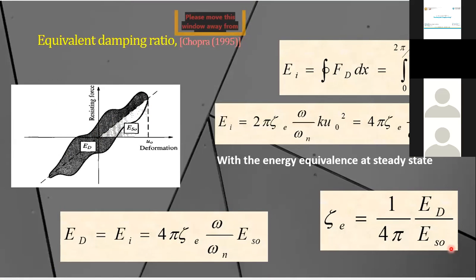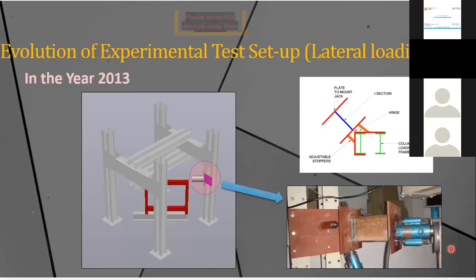As you can see in my table, we have calculated E_D and E_so, and from there we calculated a cycle by cycle damping ratio. From there we found that with the distress, with the damage, the damping capability of the infill or RC frame increases. We found that a typical value of around 2%, 3% or 4% goes as high as 8% or 10%, and this is very similar to the work that you find in literature also.